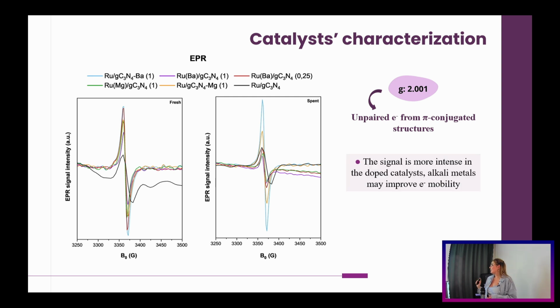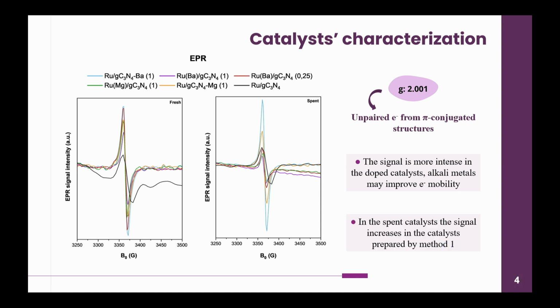This signal is more intense in the doped catalysts, which indicates an increase of unpaired electrons on the aromatic system and an increase of nitrogen defects. This means that the alkali may improve electron mobility. Also, the signal increases in the spent catalyst prepared by mixing the alkali and the urea before the thermal polymerization, while the signal decreases in the spent catalyst prepared by co-impregnation.